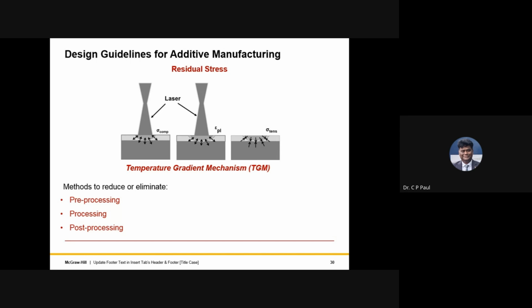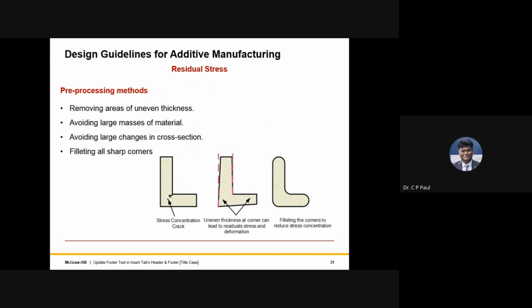Specifically, when we are talking of residual stresses, what should be our strategy which will make things comfortable for us to move and work further? For example, if you want to use some pre-processing methods, you can remove stress concentration cracks, wherever they are likely to happen. You can remove uneven thickness. We also try to avoid large masses for the deposition and abrupt changes in the cross section. This will help us, and this can be done by filleting all the positions.